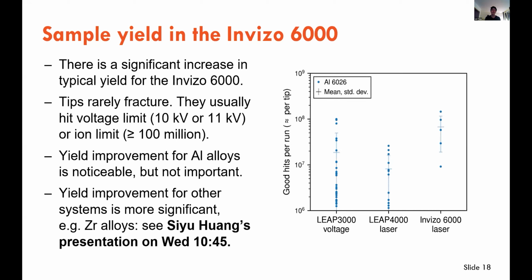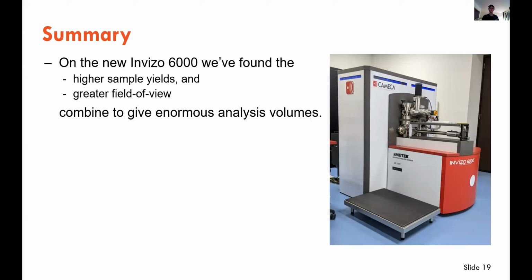So yield is more important for other LEAP systems though, particularly where tips had a lot higher likelihood of fracture. So Siyu Huang is presenting tomorrow on zirconium alloys. He talks more about yield in the Invizo 6000. I'd urge you to see his talk to see what effect it's had on his work. So to wrap up, on the Invizo 6000, we found that when you have high sample yield, tips run, and greater field of view, recon is wide, you get enormous analysis volumes. And this is really exciting for when you had sparse precipitates or you wanted better counting statistics for chemistry, for geometry, for a lot of different things.